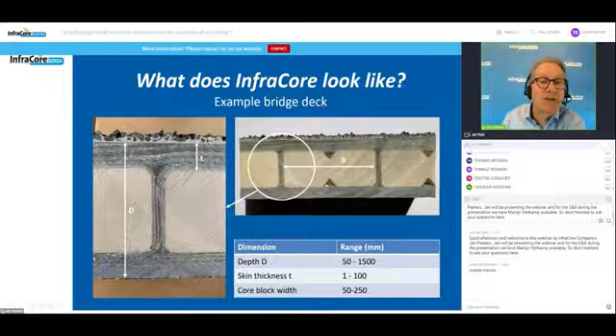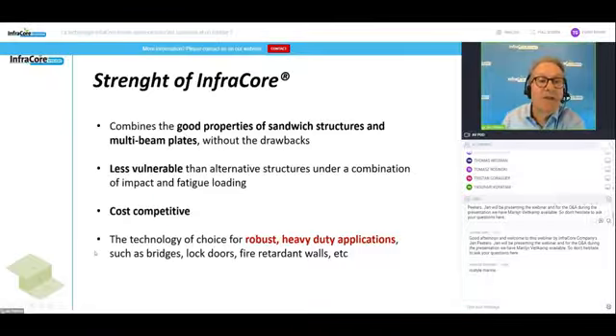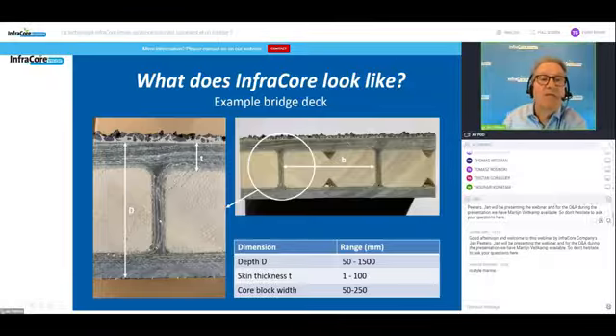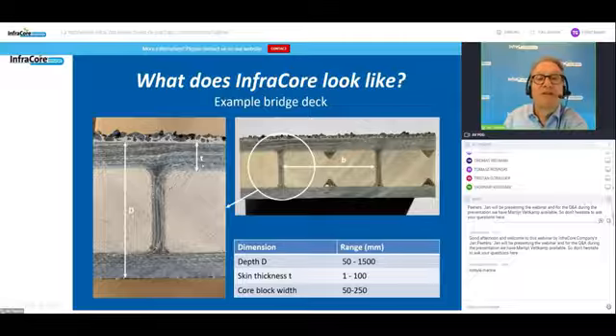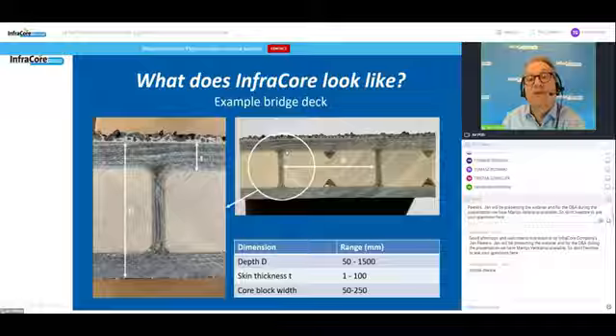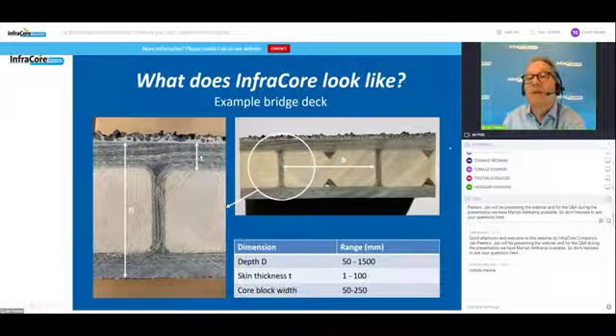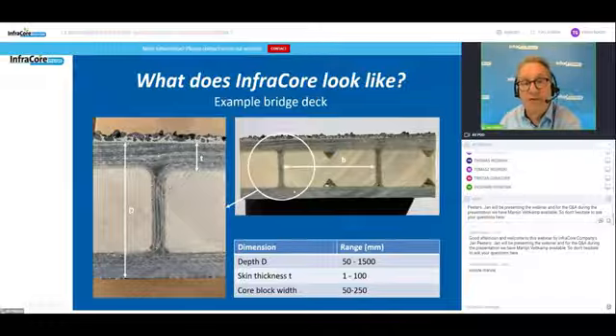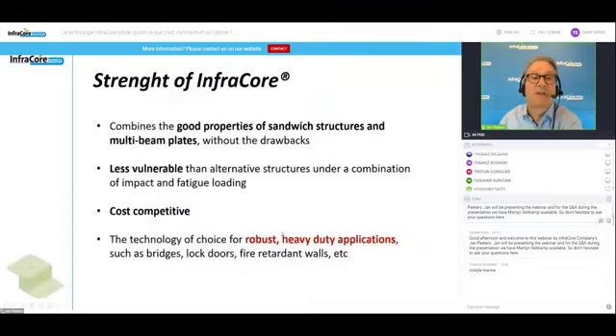If you look closely, you can see the Z layers here. The Z layers running here jump to the other side and they continue here. And if you look at the scale, you would see that the fibers which are here in the underlayer will step up a little bit and they end up in the top skin something like 50 centimeters to the right. And this layer will end up in the skin somewhere 50 centimeters to the left. Well, that is how it looks.